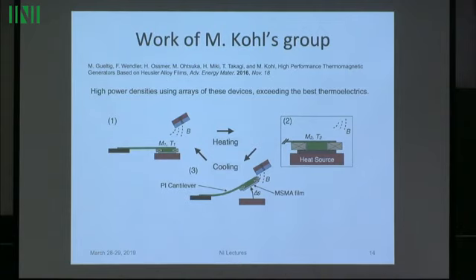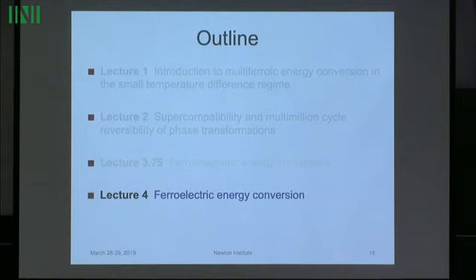We said, well, maybe ferroelectricity is better. When you do ferroelectricity, you think in energy conversion. Instead of induction, we're going to use capacitance. So we're going to use capacitors. That's the natural way to think in ferroelectric energy conversion. And if you use capacitors, they have this big free surface. They're very thin, the thinner the better, as we'll see in a minute. So you have this very big surface where you could do heat transfer. You can point it at the sun. You can do whatever. So it seems like a better thing, and we started working on ferroelectric phase transformations.